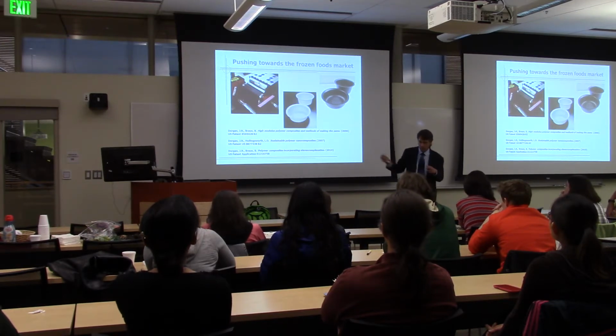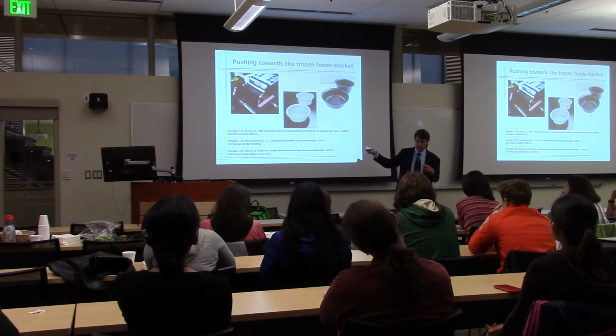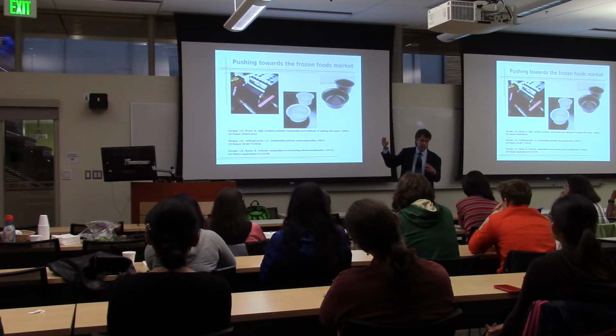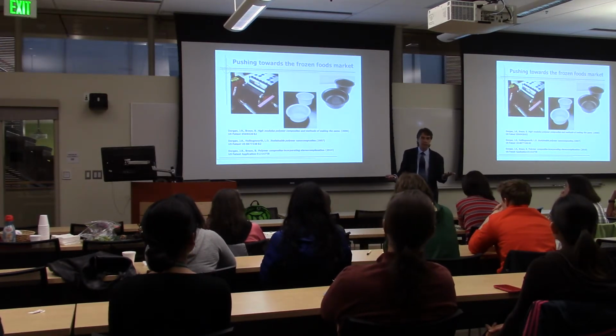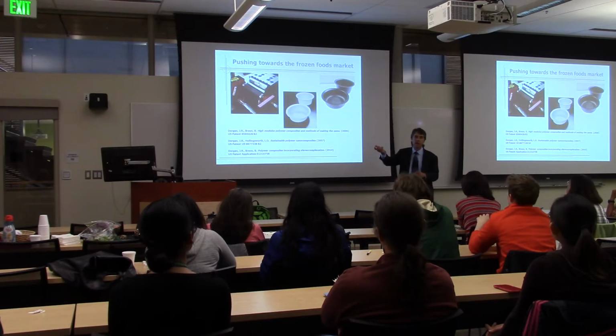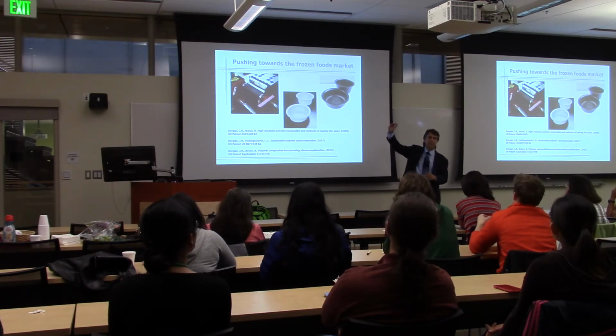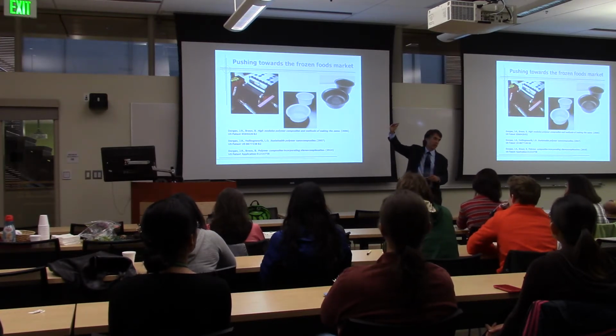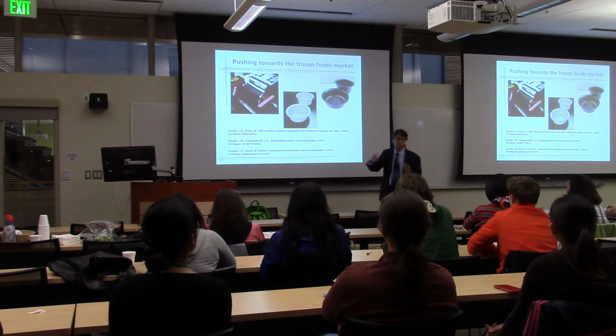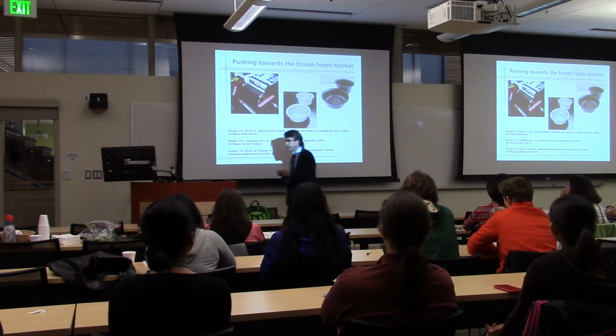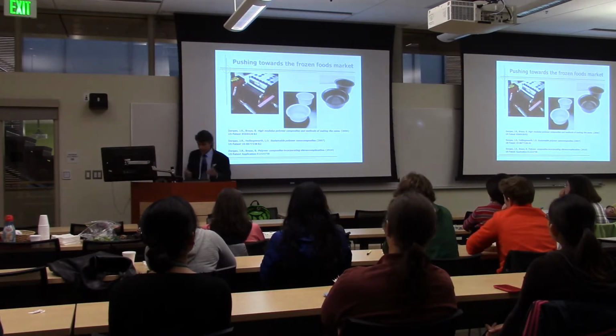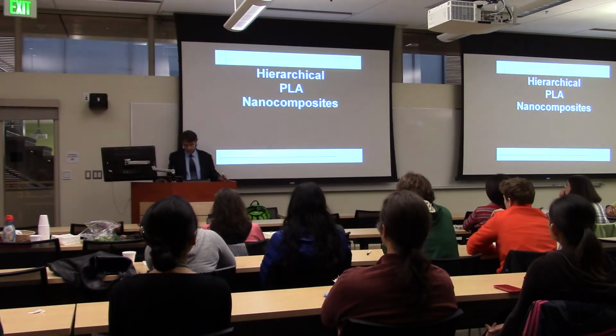If you pull your frozen dinner out of the freezer and it slips out of your hand and falls on the ground, you need to have very good crack resistance at 0 degrees C or colder, right? So the material has to be able to be impacted at very cold temperatures. Then you put it in the microwave and heat it up to 100 degrees. So now it has to have dimensional stability at 100 degrees centigrade as well. It's really incredible that we have materials that will do all of that, and it was much more demanding than you might think to get this to work.